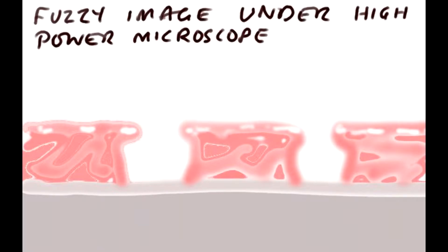If you're using a silicon or gallium arsenide substrate and you form some photoresist stencil, you can cleave across the substrate, turn it on its side, and look at it from without an SEM on a microscope. If the resist is about one micron thick or more, you can see the profile, so you can check whether you're getting a lift-off profile quite easily with a microscope.